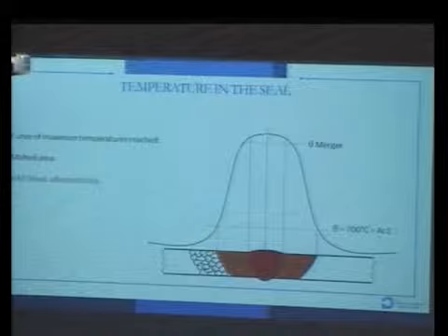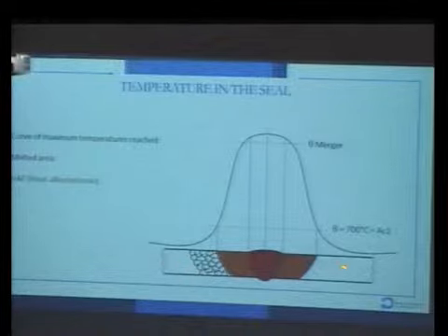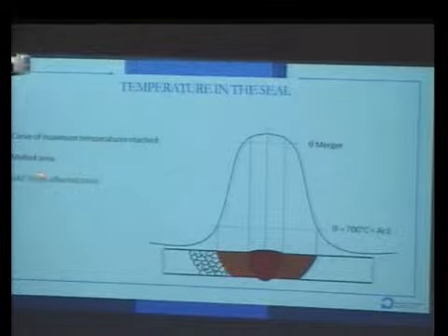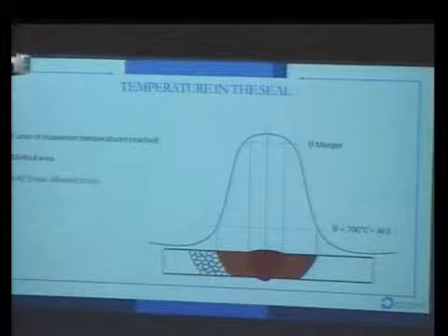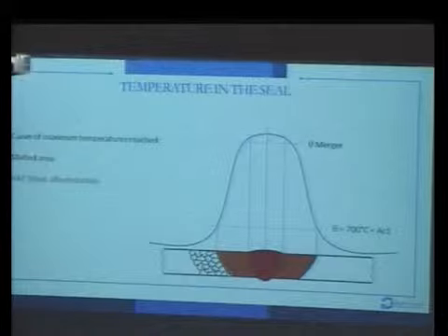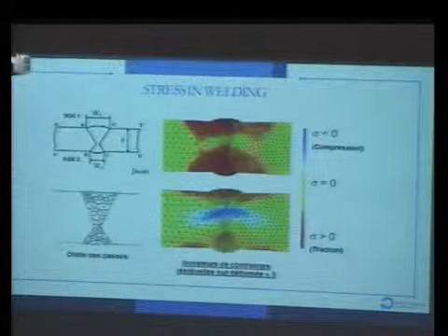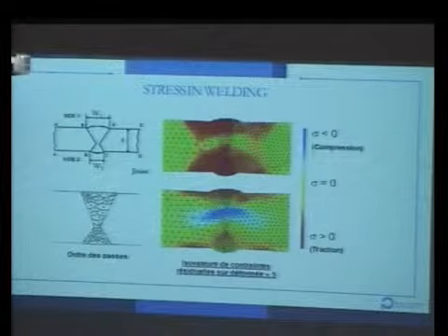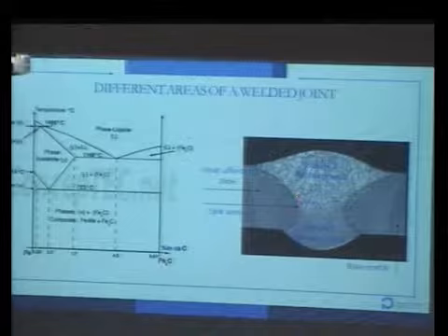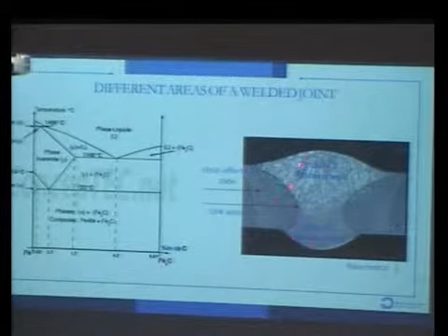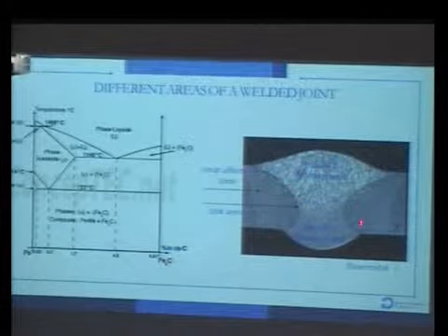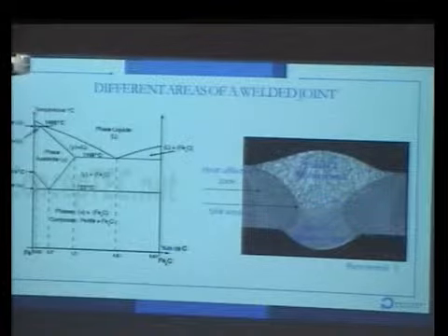And here, when you weld, you have here the welded zone. By definition, this welding zone is higher than 1500 degrees because we melt it. Here, far away from the weld, you are at normal temperature, but between, you have a zone named the heat affected zone. It's a zone in which we are higher than 900 degrees, and for the iron steel, we have a change of structure. We have stress in here, for example, you can see the molten zone pass 1, the molten zone pass 2, and here on two sides you have a heat affected zone, the zone in which the metal was transformed.